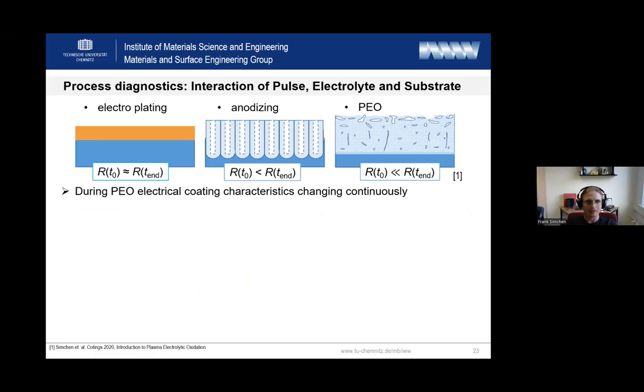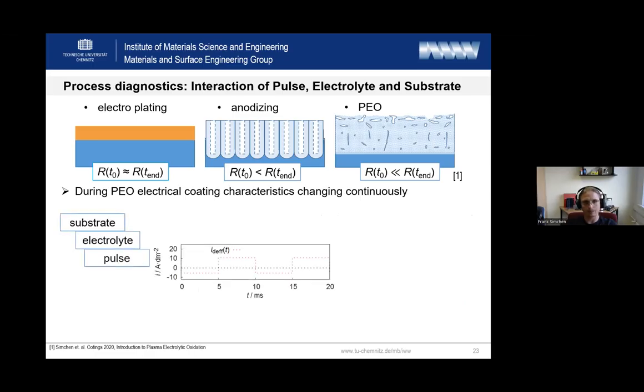Okay, but then we still come to the situation that we have input parameters: substrate, electrolyte, and electrical pulse. Then we apply 1 hour of plasma discharges and all these substances are catapulted from solid to liquid to gas to plasma and back 100 times per second, within some milliseconds. And after 1 hour, we receive a coating, and now we need to understand what happened here.